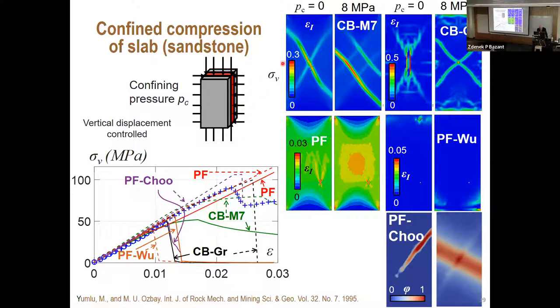Zero, different pressure. Different values, okay, so different values. Or here, zero or 8 MPa. So you get this pattern, which agrees well with the experiment, or this at high load, you get this. Now, CB-M7, this is correct, but this is not really correct. Pereira, phase field, completely wrong. Phase field Wu, wrong. There's an interesting improvement by Professor Choo from Korea, which I don't have time to discuss, but we ran it for this case. And that also seems to work here, but not for higher compression, only for the low compression.